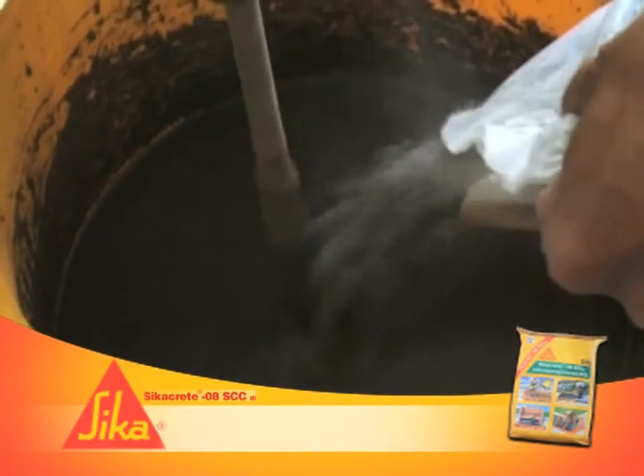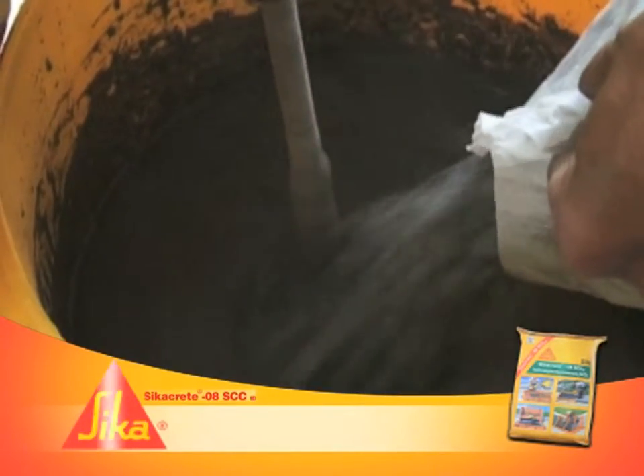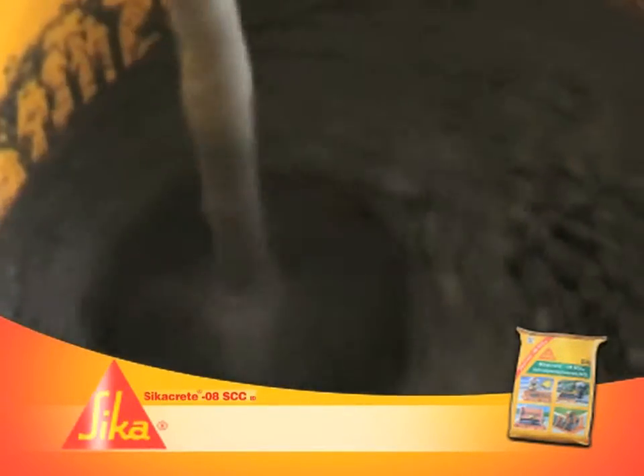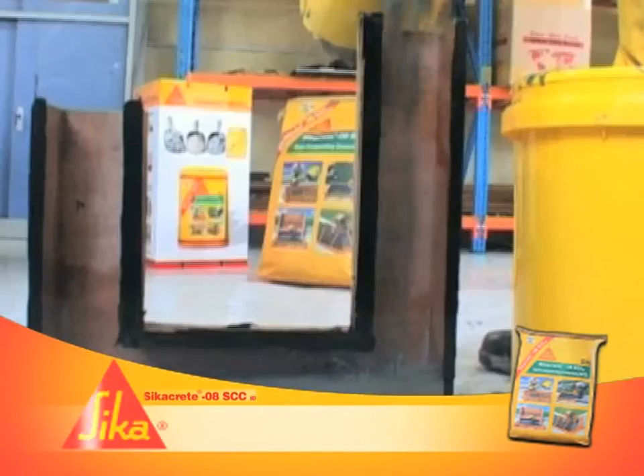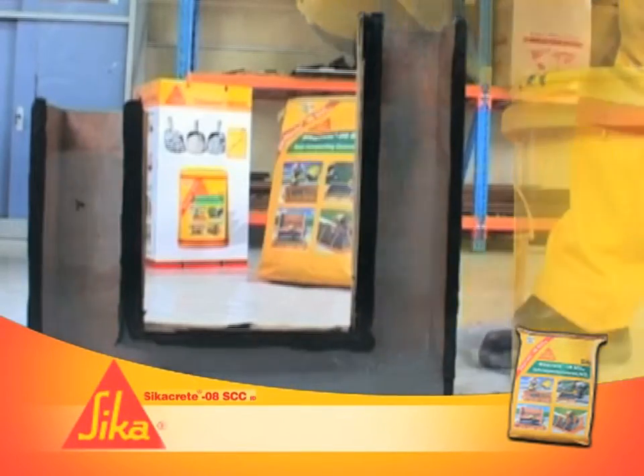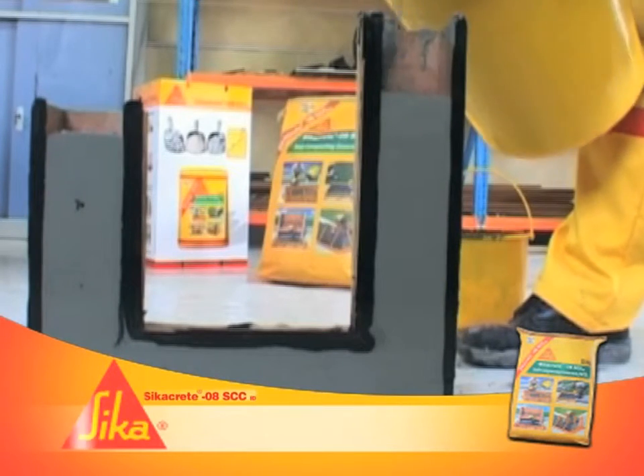Mix continuously for 2 minutes and then add the aggregates. Mix with a low-speed mixer at 400 to 600 RPM. Using a pan mixer, add Sikacrete 08 SCC and mix for a few seconds. Add water and mix at a low speed for 3 minutes.